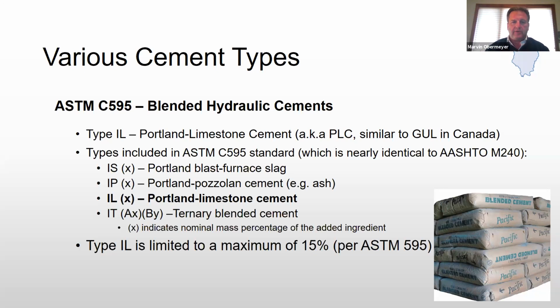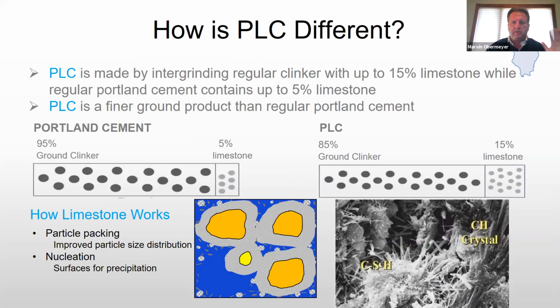Type IL, that's what we're here gathered to talk about. Portland limestone cement, where calcium carbonate or limestone is added to the cement, and the X value is some number between 5 and 15%. Type IT, which you hardly ever see, is a ternary blend where it usually has a fly ash and/or a slag. Usually that's the blend there. Type IL is limited to a maximum of 15% per ASTM C595. So that means that the parentheses, we won't go over 15% there. Usually when we're selling a product like that, we'll designate and tell you what the percentage is for that particular plant.